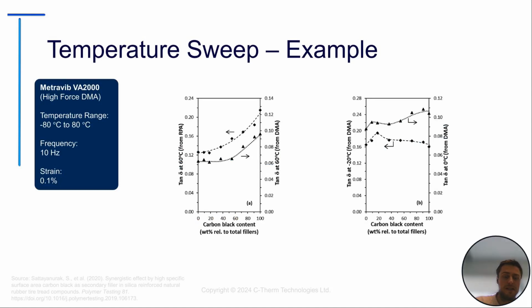And what they did was they did temperature sweeps from -80 to 80 degrees Celsius with a high force DMA, with a frequency of 10 hertz and a strain of 0.1%. If you've attended one of our previous webinars, I mentioned how every ASTM standard will have a specific frequency you can test at, usually between 1 and 5, but a lot of the times in the tire industry, you'll see around 10 to 12 hertz, and that's just to replicate the rotational motion of the tire.